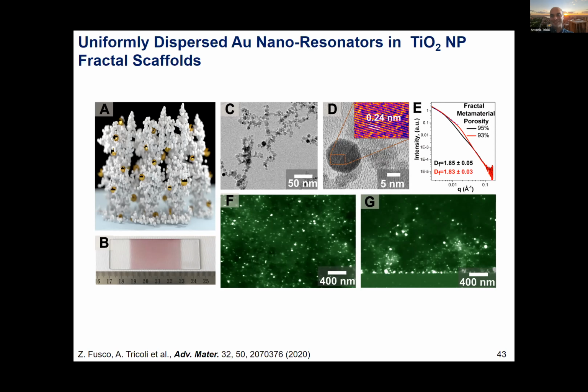So we didn't study it yet. The difficult part is that you have obviously to compare as a function of the surface area. When you start increasing the fractal dimension, remembering that 3 is a fully dense sphere, so 1.8 is this aerosol deposition, and 1 is a line. So basically the surface area becomes less. So obviously we have to put more material or scale it for the surface.